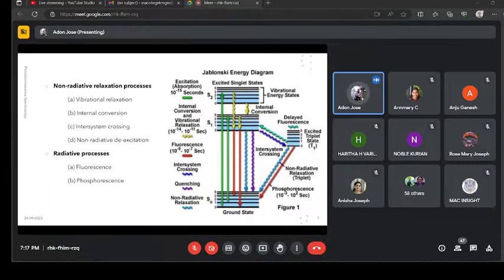Here, the non-radiative relaxation processes can also occur between excited states of different spin multiplicity. Here we can see that there is a transition from this S1 to the triplet excited state. Both of them have different multiplicity: one has the singlet state, whereas the other is the triplet state. This is referred to as inter-system crossing.